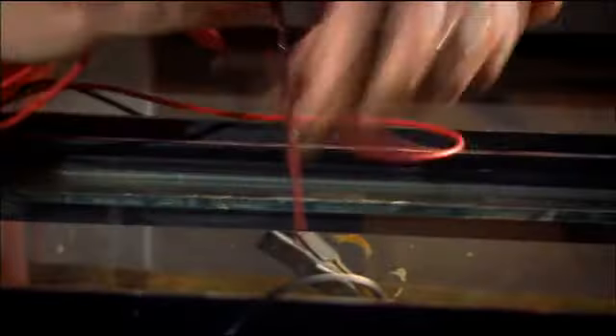So disconnecting that plate, and it hasn't eaten through. I mean, nothing. It's done nothing to it. It's fine. It's just got a little bit of slime on the surface. And the difference in here is that zinc block. How's that work? Well, the zinc here has actually been corroding preferentially. It's been sacrificial to the steel. Actually, this isn't the original zinc block. That's been eaten away already. We've had to replace it.